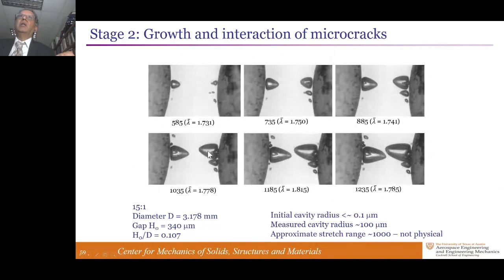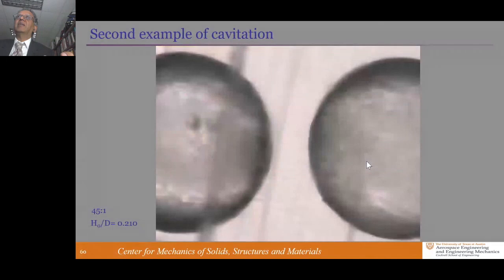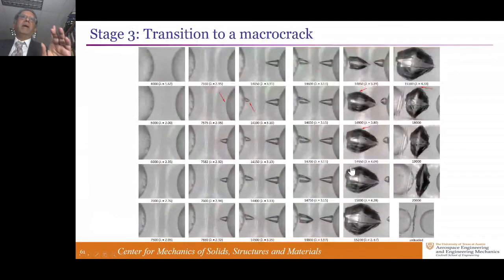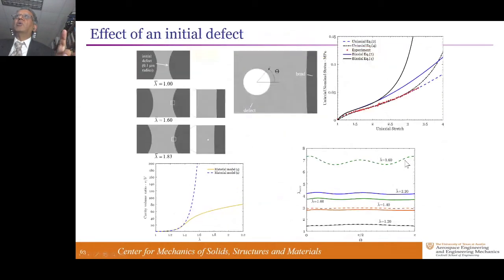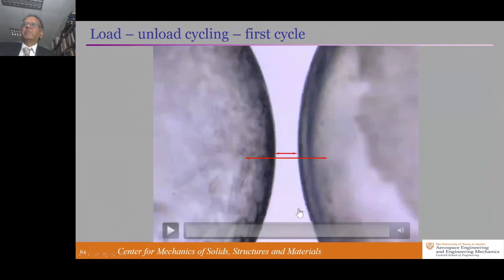If you look at a later stage, the picture is even more dire. Stretches are on the order of 1,000. This really is a crack, and we've been able to show that by unloading it and looking at that. I want to skip all of these things and go to one final picture, which is something that happened serendipitously. We unloaded the specimen and found that these cavities were closing back up. And I'll show this by one experiment.